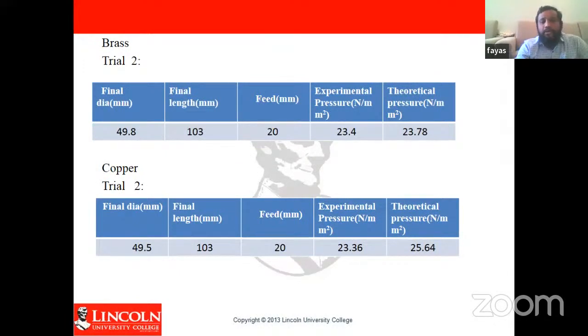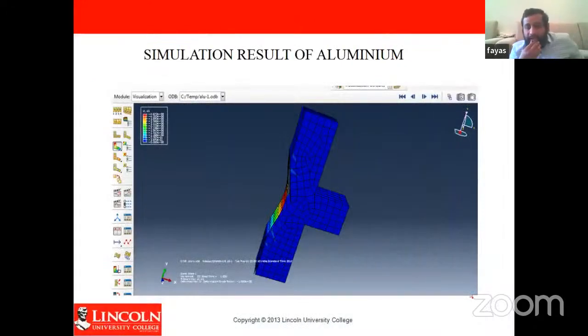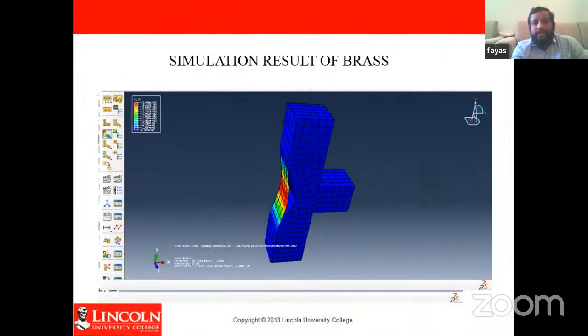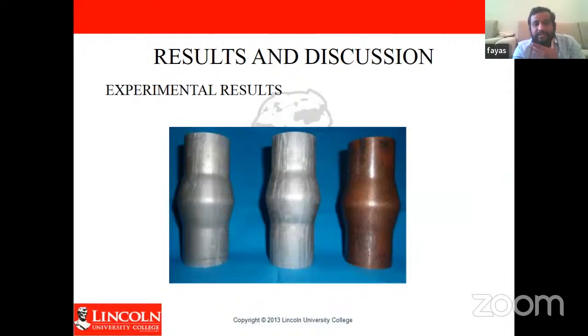Copper also we got at 20 millimeter feed, in the second trial. And then this is the simulation. We did it in Abaqus. We did all the pre-processing and post-processing. This is only the final results of aluminum, brass, and copper. We note down the values. So these are the experiment results for aluminum, brass, and copper. This is our final output from the experiment.